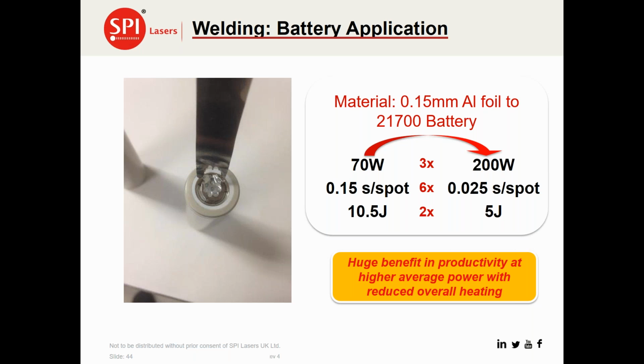This is an application again around batteries, where we are welding 0.15 millimeter aluminium foil to a battery cell. We're finding actually that we're now getting huge benefits in productivity at higher average power with reduced overall heating. In fact, for roughly a 3 times increase in average power from 70 watts to 200 watts, we're seeing a 6 times increase in the speed. So a 6 times reduction in the time per spot, and a halving of the overall energy for a given spot or for a given weld.